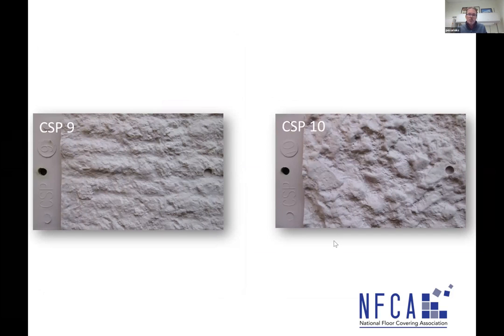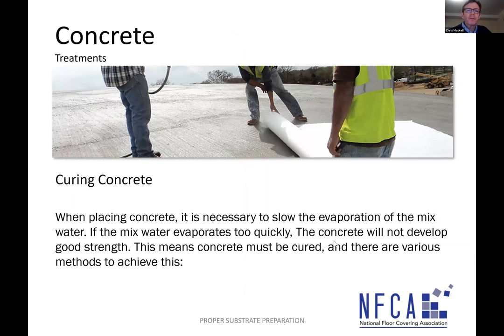It's a great tool to have in your bag to confirm that the proper profile has been achieved on the concrete surface. Seth, just a comment. If you're installing resilient flooring, we're looking for a CSP of typically two. And if you're pouring hydraulic cement, is it right? You're looking for a CSP of three? I would say the moisture mitigation systems will require a minimum of three.